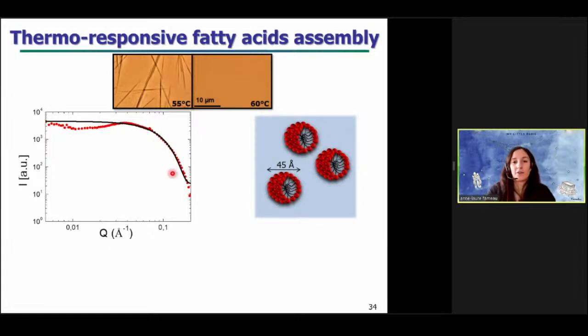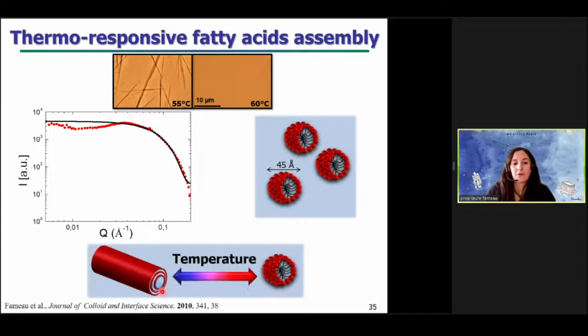And you can see that the curve is completely different from the previous one. You don't see the bright peaks anymore. And we can easily fit this curve with a form factor of a sphere, showing that spherical micelles with a diameter of 45 angstrom are present at 60 degrees. So these big micron-sized multilamellar tubes transit precisely at 60 degrees into spherical nanometric micelles. And this transition between the two states is completely reversible.